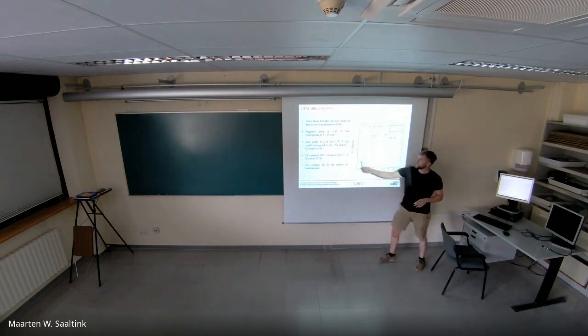Also, we observed 2 peaks at 2.16 and 2.92 angstroms that, this is my guess, could correspond to aluminium-sodium and aluminium-chlorine paths respectively. This is because chloride occupies sulfate vacancies, since the aluminium-sulfate distances are around 3 angstroms, but since we have released sulfate there should be a peak here, but there is not, so there is another thing occupying its vacancy, which is